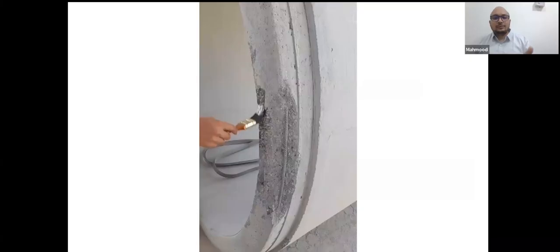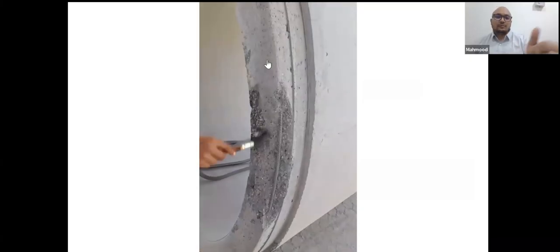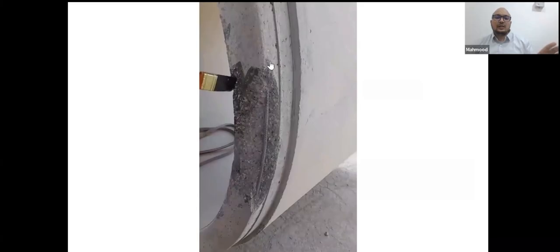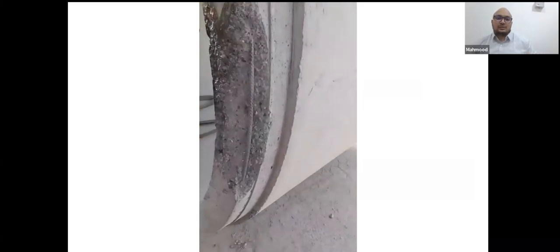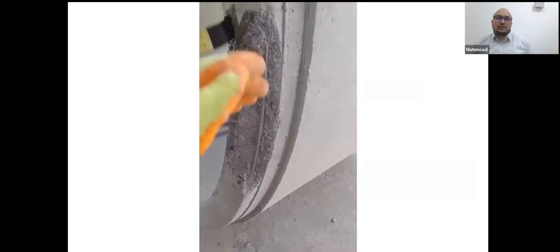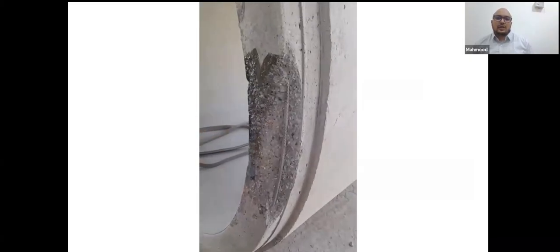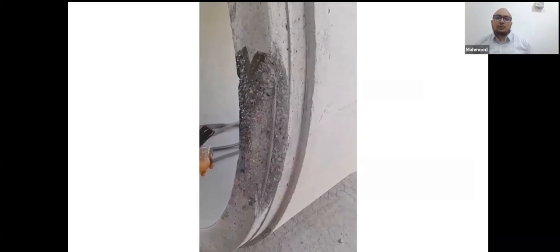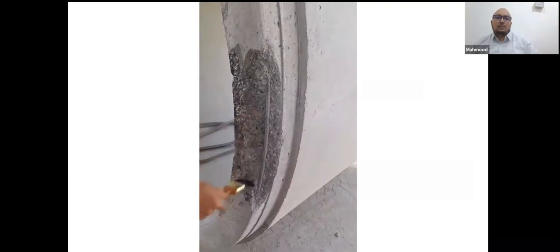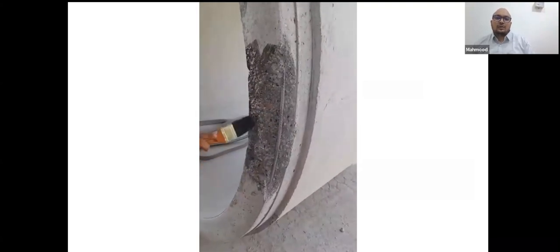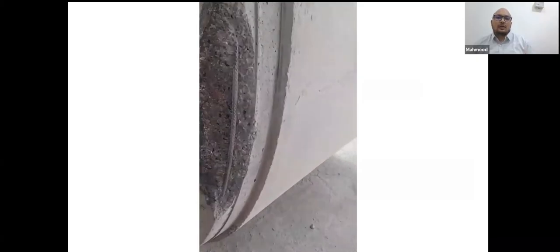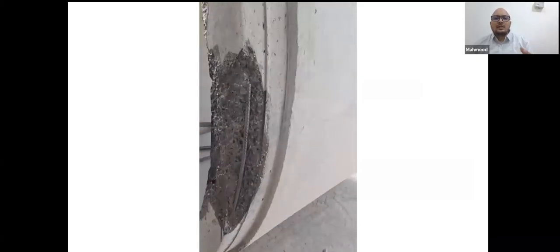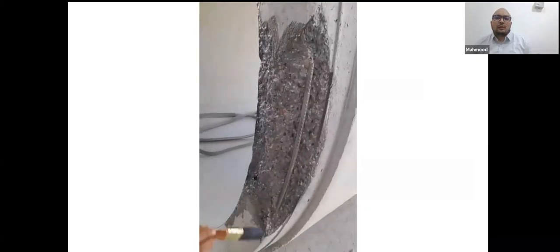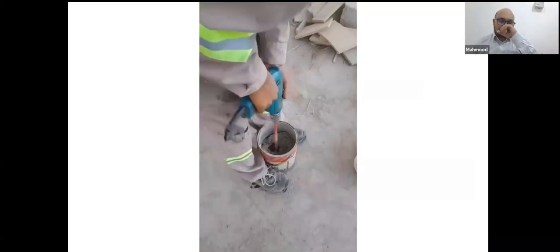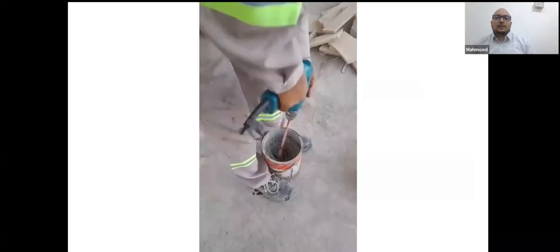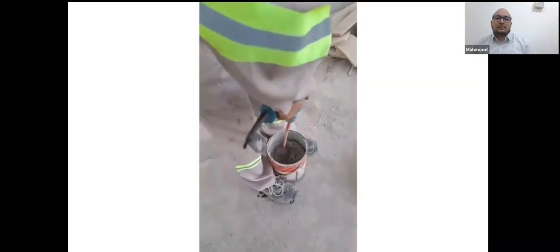The same epoxy repair mortar is being used for this big concrete pipe which they bury under the ground. They use it for the tunnel, to discharge the waste from the sewage treatment plant to the sea. These pipes are being pumped inside to the sea, so they should withstand that much load. Unfortunately, during the production stage, some edges will break. They cannot throw away the complete pipe; it will be a loss. So they need to repair it with the high strength epoxy repair mortar.